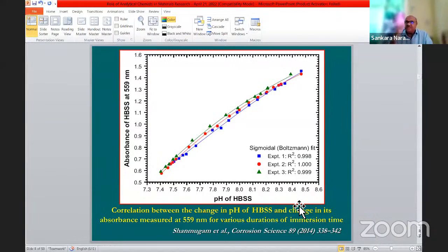We already said that if there is a rapid change in the pH of the HBSS solution, then there is a rapid increase in corrosion. So if we follow the absorbance measurement, and the absorbance is very high, then automatically we can say that the rate of corrosion is very high. So why do we have to use absorbance measurement? People may ask why we have to use absorbance in the spectrophotometric method when monitoring the pH is a much easier method. Definitely, I agree that pH measurement is the simplest and easiest way to monitor the change.